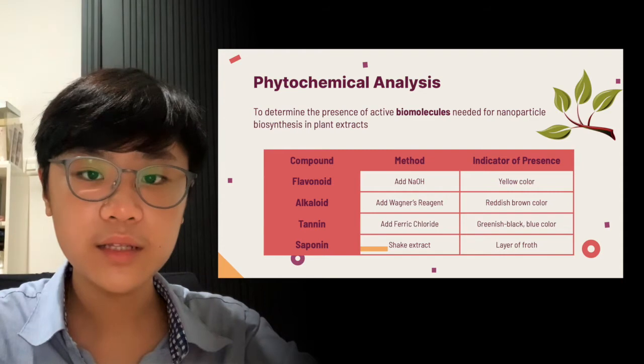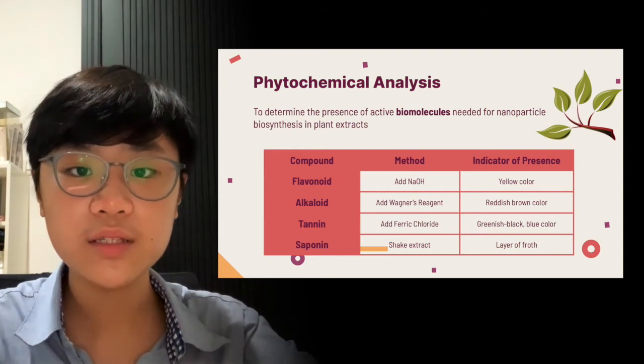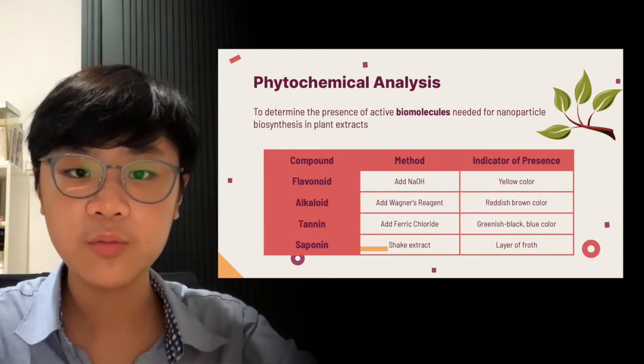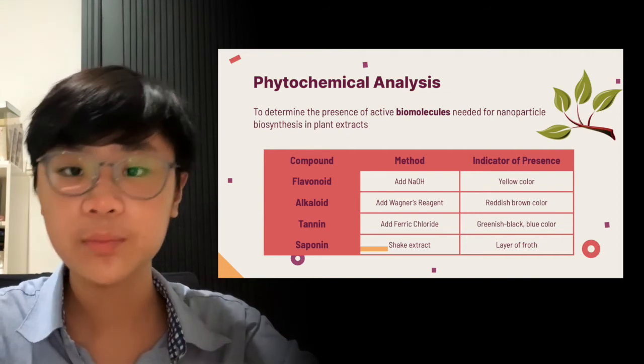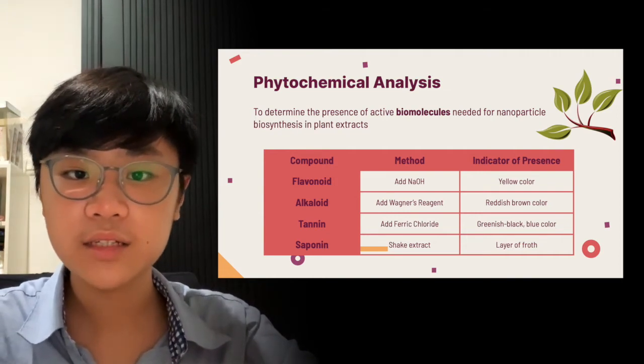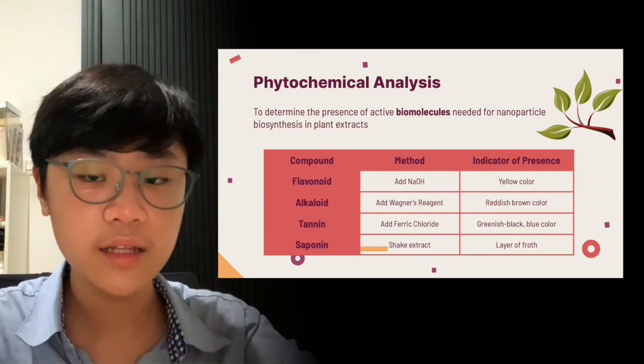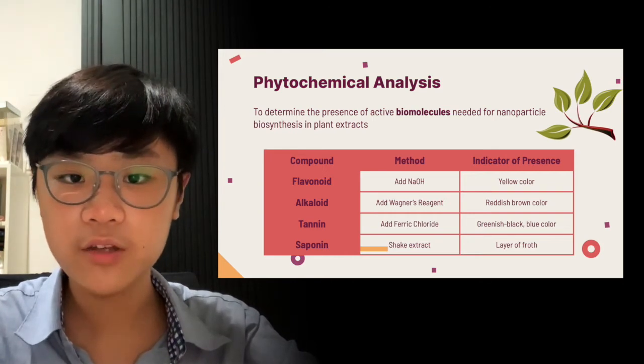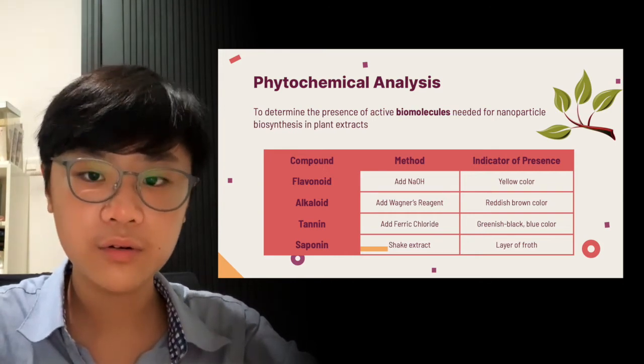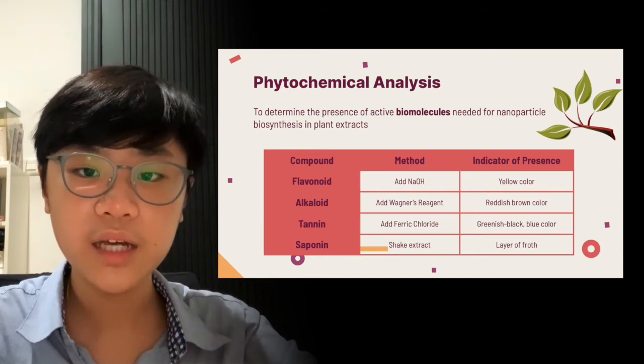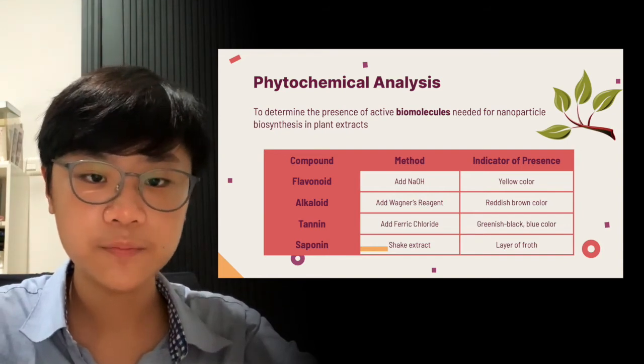The phytochemical analysis is conducted to determine the presence of active biomolecules needed for nanoparticle biosynthesis in the plant extract. The compounds tested are flavonoids using sodium hydroxide, alkaloids using Wagner's reagent, tannins using ferric chloride, and saponins, which can be identified by shaking the extract.